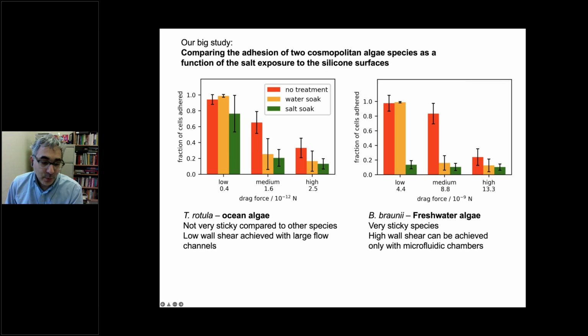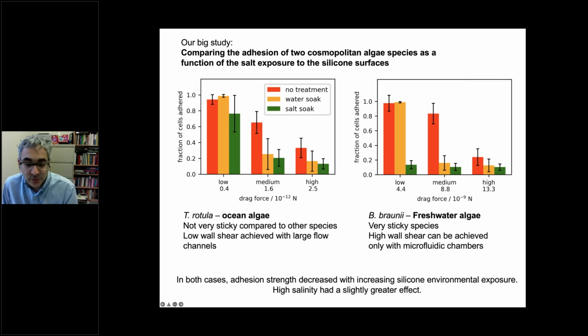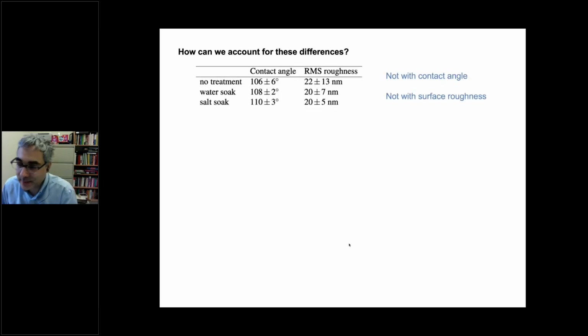areas. And in both cases, what we found is that the adhesion strength of the algae decreased with increasing silicone environmental exposure. In other words, the algae were more likely to come off the surface or not as strongly adhered onto the silicone if there was treatment with either water or salt water. And the salt treatment had even a greater effect in the sense that the algae wasn't adhered so strongly. So this is very fascinating, and we wanted to understand why this is the case. So now it comes back to the materials problem. How has this environmental exposure actually affected the silicone rubber? What's happening there to make it more or less susceptible to the cell adhesion?